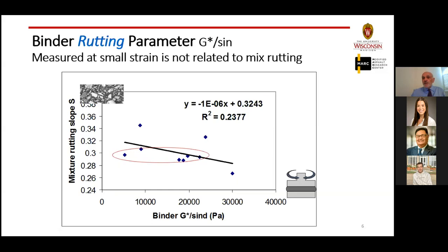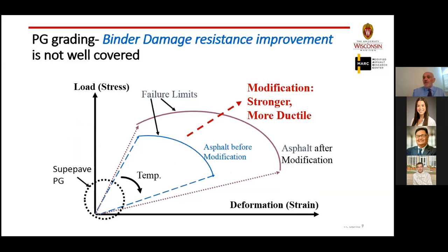When we took these binders and tested them in a slightly different way, and took them to the level of damage, to the large stress and the large strain, we could actually find much better correlation with the behavior of these mixtures. As most of you probably know, the future of the asphalt industry is in modification and recycling. And when you use more recycled material, or more modifier, you totally change the behavior of these binders and these mixtures.